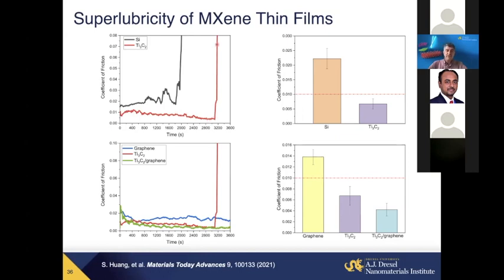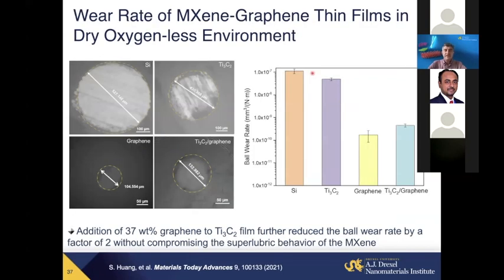And while at a certain point there is a sharp increase and breakthrough, if graphene is also added to it here, probably preventing it from wearing through the MXene films, larger graphene flakes may kind of stabilize, coat them, shield them here. There is basically continuous superlubricious behavior over a very large number of cycles here. So this combination actually appeared to give even better properties compared to pure Ti3C2 and significant improvement compared to, say, graphene or just the surface, uncoated surface of silicon here, with also much smaller wear scar and excellent performance here.